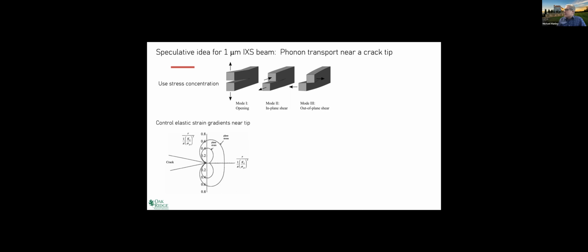But it's also a place where you can control things. You can create different strain states. You can create strain gradients. You can load regions with dislocations by moving the crack a little bit, depending upon the material, to create a plastic zone. And so if you have a 1 micron beam, you could go in there and measure phonon lifetimes in different regions with elastic strain gradients or high dislocation densities, things like that. That's just something I'm putting out there as a speculative thing to think about.